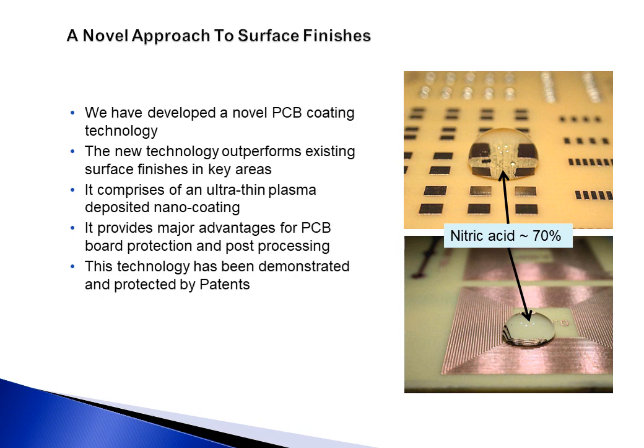Now, one of the interesting things that I'd like to point out about this slide is that the bead of liquid that you can see sitting on that circuit board is actually highly concentrated nitric acid. It will sit there for about 20-25 seconds, long enough to get a photograph, before it actually starts to burn through the coating and attack the copper underneath. But to get this photograph, you have to have the board sitting perfectly level. The slightest tilt on it and that acid will just run straight off without affecting the board.